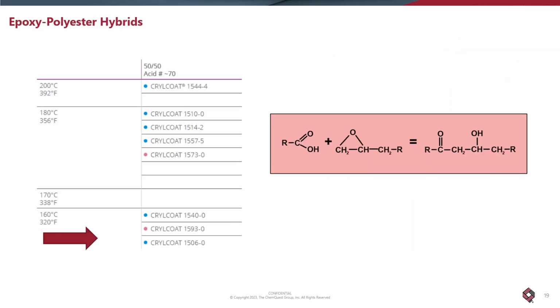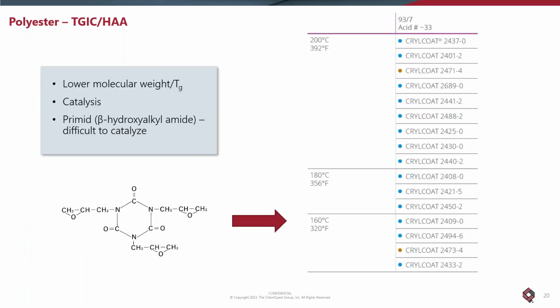Now, epoxy polyester hybrids, and this is one where our friends at the polyester resin companies have done a nice job of introducing pre-catalyzed, lower melt point, lower melt viscosity type polyesters. You marry those up with a corresponding kind of lower melt viscosity epoxy resin, and you've got something that's going to cure nicely at the 160 degrees Celsius range. The polyester world, curing agents in powder coating world, TGIC or HAA, also known as Primid. Again, the polyester resin people have provided an easy way for you to lower the cure requirements for the finished powder down to 160. This is easy peasy, my friends.